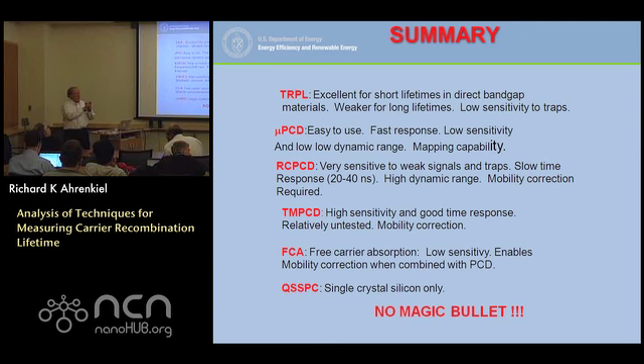Well, the three things, you can vary the injection level, you can vary the wavelength, and you can vary the temperature. And all three give clues as to what's going on. Now, we had discussed this morning about traps. At one point, we had a PCD system that was in a cryostat, and that was ideal for looking at traps, because if you see these long tails, like we've seen recently, these long decay tails, and if the decay time increases as you lower the temperature, then you know this is an Arrhenius behavior. So there's a delta E over kT effect there, which is a trapping effect. So you can be fairly certain that you're looking at traps.